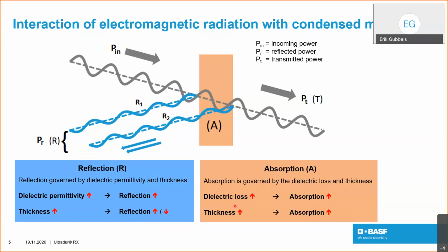Also, the thickness plays a role on the absorption, where typically one can say that if you increase the thickness of an absorber, the absorption will also increase. However, this is not always the case. At the end, there is still the transmission left, and the transmission is nothing more than 100% of the incoming power minus the reflected power minus the absorbed power, and here is denoted as PT.